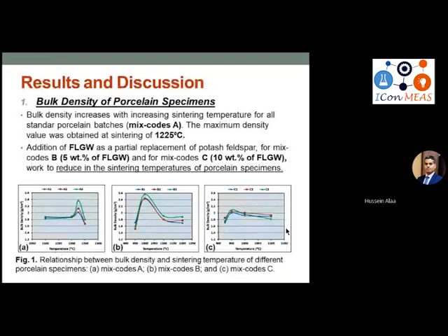Results and discussion. Firstly, the bulk density of the standard porcelain specimens. The bulk density increased with increasing sintering temperature, as shown in Figure 1A, increased up to 1,225, and then decreased. This increase is due to the increased contact between particles.